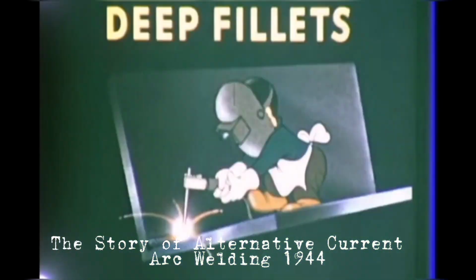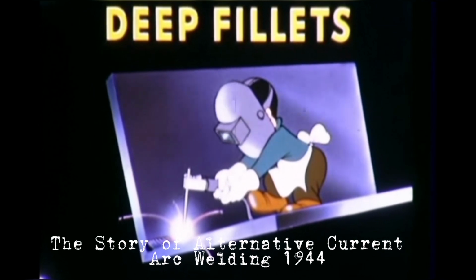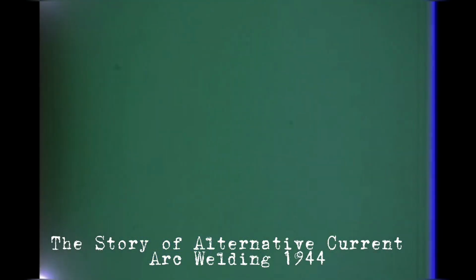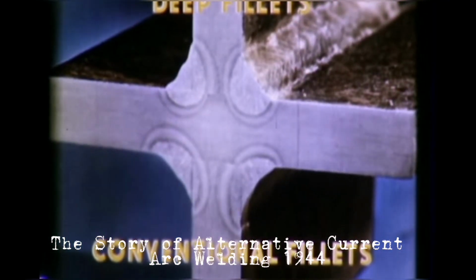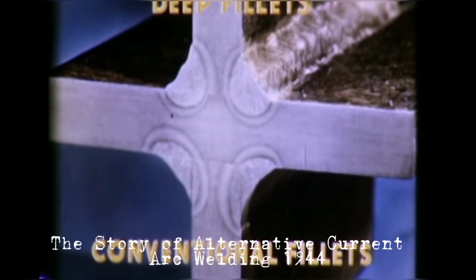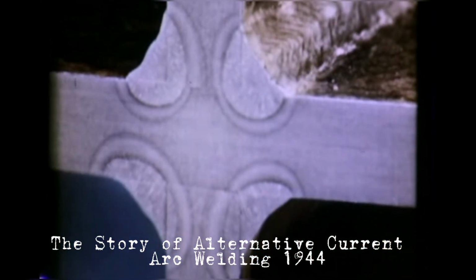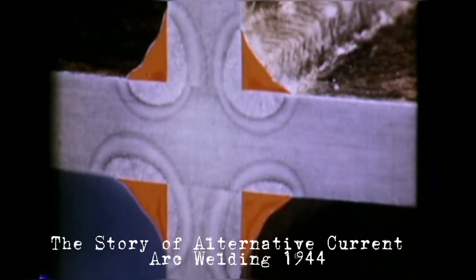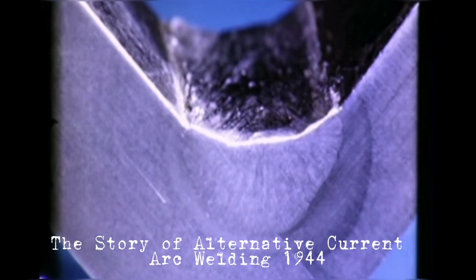Deep fillets, as the name implies, have deeper fusion than fillets made with normal technique. Deep fillets are made in either the flat or horizontal positions. The gauge size of the deep fillet and the amount of filler metal required to make it are smaller than in the normal fillet of equal strength. The all-important factor, whether in single pass fillets or in the first pass of multi-layer fillets, is uniformly deep fusion.